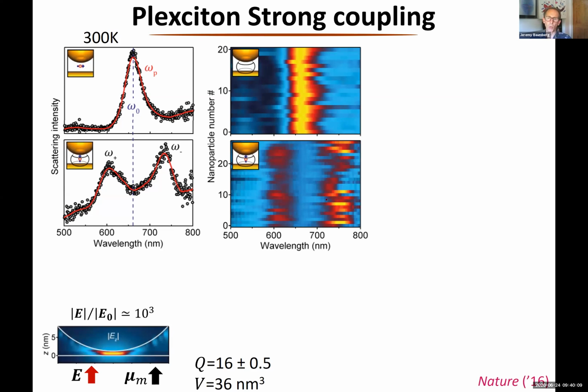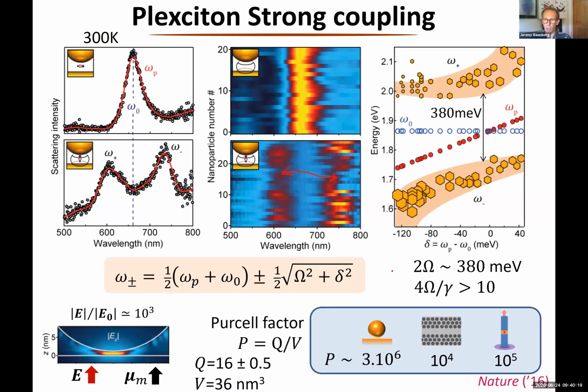So this is a whole load of different samples, and you can see each one of these is a particular nanocavity or nanoparticle on mirror sample with a dye molecule in, and all of them have this nice anti-crossing, and you can just plot this out. Because they have slightly different sizes of nanoparticles, the most difficult thing to ensure is that the diameter of the nanoparticles is all the same. So even if you try very hard, you typically have 3 to 5% size variation, and that's what gives you a variation in the tuning condition between the plasmon and the exciton. So you can actually see this very nice strong coupling going on there. What we think is we have mode volumes on the order of about 36 nanometers cubed, but the Q is not very high, but that's fine in this system. And that leads to strong couplings of around 400 millielectron volts or so.